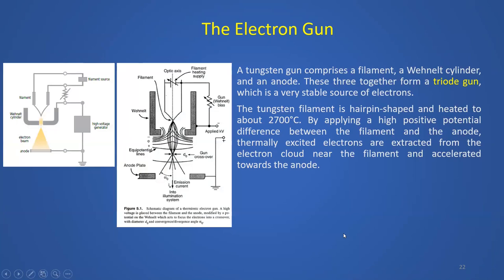Okay, so coming to each component now, the electron gun is similar to that of a TEM, so I won't be discussing it in too much detail. This is a tungsten gun, which comprises a filament, a Wehnelt cylinder, this is the Wehnelt, and you have an anode here. This is typically called a self-biased gun or a triode gun. By thermionic emission, there's a hairpin tungsten filament here, heated to temperatures around 2700 degrees centigrade. By applying a high positive potential difference between the filament and the anode, you can thermally excite these electrons, and they travel at very high speeds through the anode.